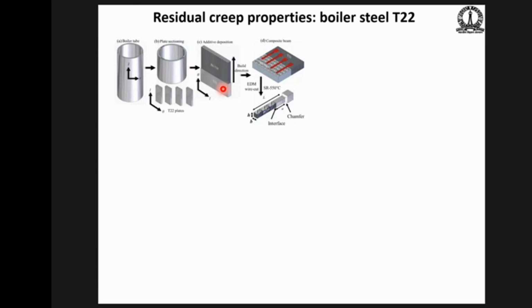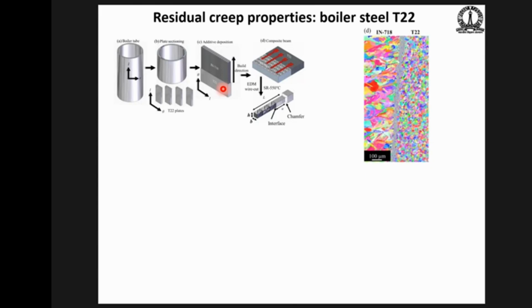So you can reduce the size of the coupon and increase the size of the handle, if you like, the lever arm. So we do different ratios of the two. This is the interface between the inconel and the T22. It's a very small layer. We don't believe it has much of an influence. Anyway, it holds up. There's nothing special going on there.